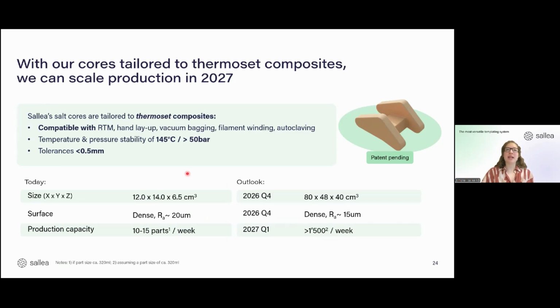Our main, let's say, limitations and points we are working on is, on one hand, the part size. So at the moment, we are working with an R&D printer and therefore are quite limited in the part size we can do. However, we are about to purchase a bigger printer to actually go to much bigger sizes. Second is the surface. I think you saw it from the case studies. We saw that there is still some remaining and it's a bit still rough. So the idea is to improve on the surface because we actually use a coating to make that even smoother. And last but not least, our production capacity, also related to the 3D printer, at the moment is roughly 10 to 15 parts per week. In Q1 next year, that will be scaled significantly with our new printing machine that we are purchasing at the moment.